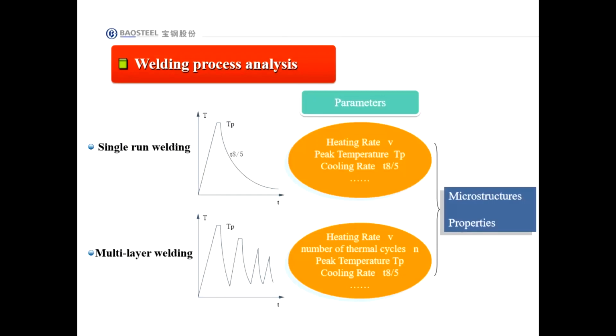Fourthly, a welding process can be analyzed using the Gleeble system. The welding thermal cycles of single-run welding and multi-layer welding can be simulated by designing a series of parameters like the heating rate, the peak temperature, the cooling rate, then the microstructures and hardness can be obtained. We can compare and analyze and then decide which welding process is good.